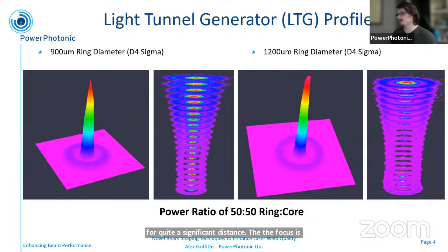We've gone for a 50-50 ratio of power. It's quite visually misleading in this image. It doesn't look like it matches up quite that way, but when you integrate under these curves, you do get 50% of the power in the ring. And there's two different geometries, one with a larger spot of 1200 microns versus the smaller 900 microns.